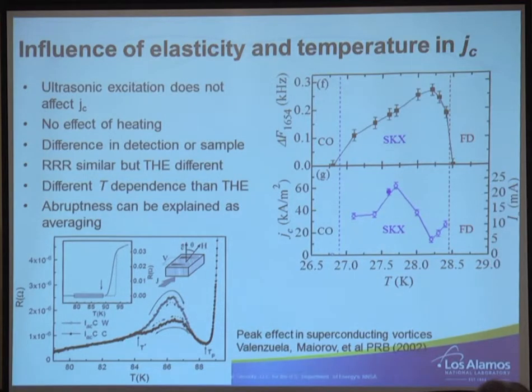But the thing I have not said is, why is this a critical current? I talk about decoupling. That's very clear, that we have skyrmion decoupling from the lattice, and our basic assumption is, well, we know that when you put current, the skyrmions will start to move. But the values and the temperature dependence that we have are much lower than the values measured for a critical current using a topological effect. We're around 1 milliamp, they are around 50 kiloamp, so it's much lower. And the temperature dependence is also different.